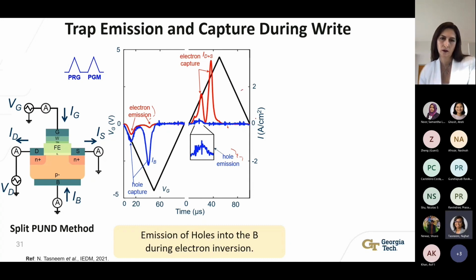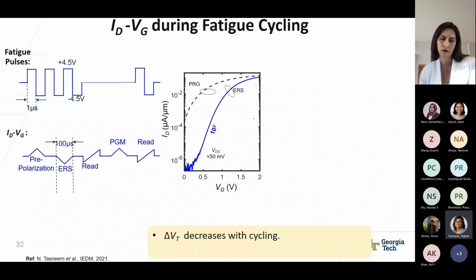So now we wanted to see how these trap dynamics change with fatigue cycling. So to observe that, we used a standard endurance measurement technique on the FeFET and measured its ID-VG characteristics for each cycling decade, shown by this figure over here, which shows that as we increase the number of cycles, the memory window keeps on decreasing, which is expected.